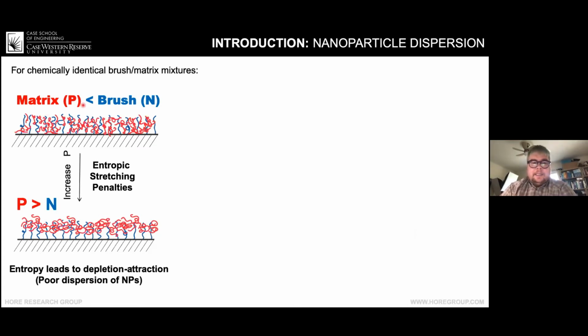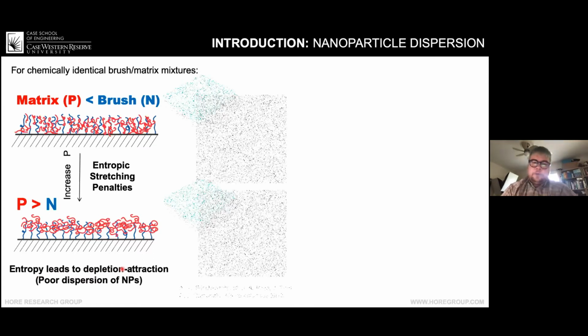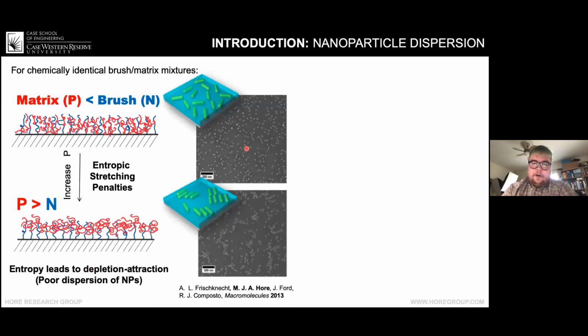And what's known is that as you increase the molecular weight of the matrix polymer, while keeping that of the brush the same, you're going to get stretching penalties if you want the red matrix chains to wet the brush. These stretching penalties are going to end up causing depletion attractions between the nanoparticles, and that's why you saw those different morphologies of the silica particles in the polystyrene matrix. From my own work, this is true for gold nanorods too. In this case, these gold nanorods are the same nanorods. They came from the same batch that was synthesized, and all that's been changed here is the molecular weight of the matrix, and you can see that the morphology of the nanoparticles is quite different.